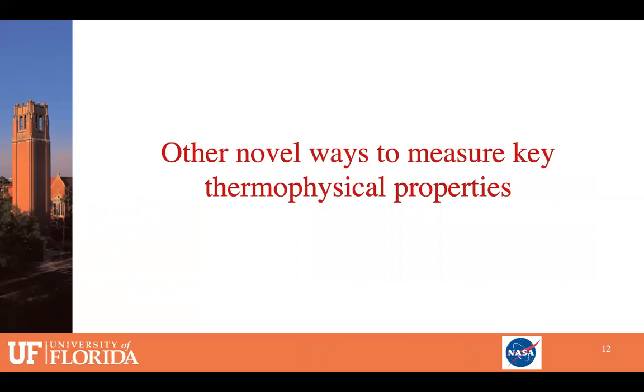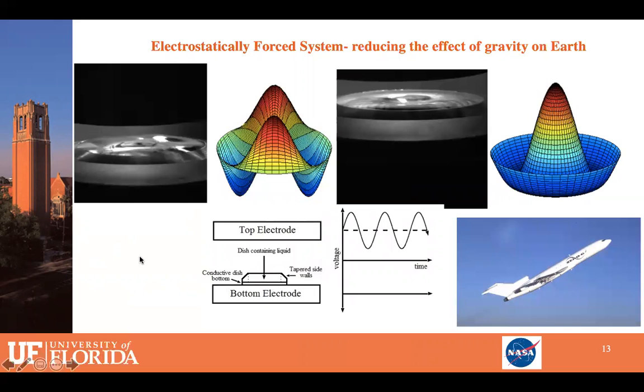Now, there are other ways to measure key thermophysical properties that do not necessarily involve levitation. One such way is to take the liquid metal and put it on a conductive dish as shown here and place the dish on top of a bottom electrode. Then apply an alternating voltage across the surface of that liquid metal. And what you'll see are a series of patterns, which I've now shown here. These patterns occur at specific, different frequencies, and these patterns and their frequencies can be correlated to the surface tension.